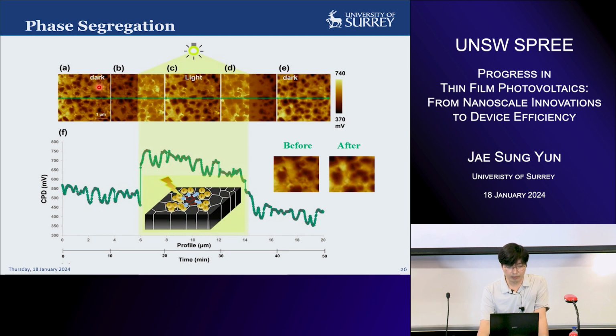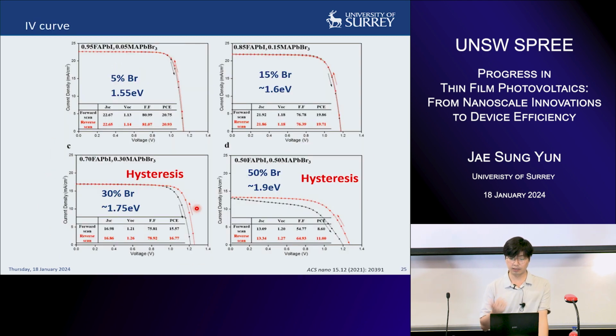So if we measure KPFM under the dark, and we continuously measure, each map takes around 4 minutes, and we measure along the dark and light illumination. We measure the same region, and we turn on the light at this point, and we turn off the light. You can clearly see that before the light illumination and after illumination is very different. That's before illumination, where you can see that the flat grain region is confined within the grain, and after the illumination it spreads out. So we think that these mobile halide ions spread around the grains and even across the grain boundaries. That's why we have a very bad hysteresis in your material before and after light illumination and during the illumination as well.